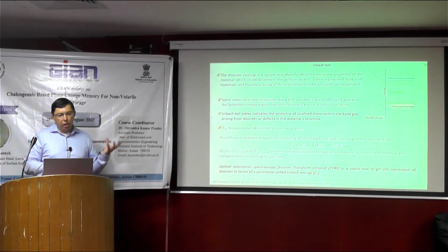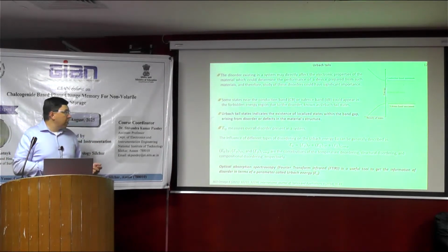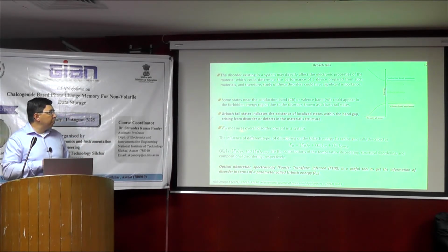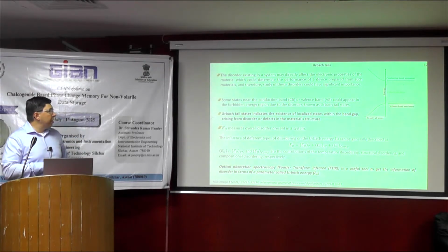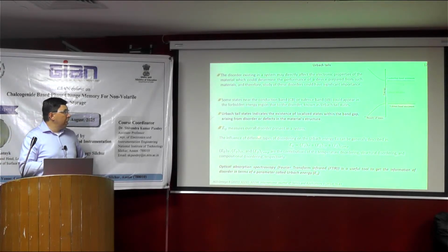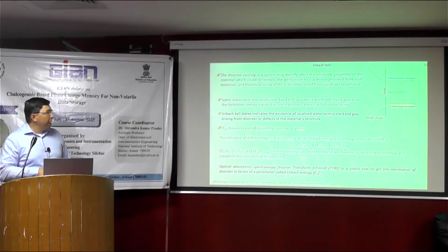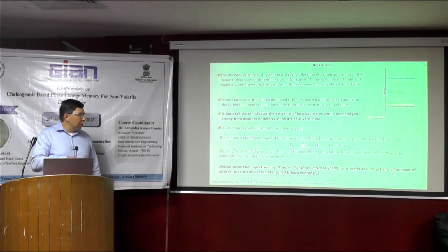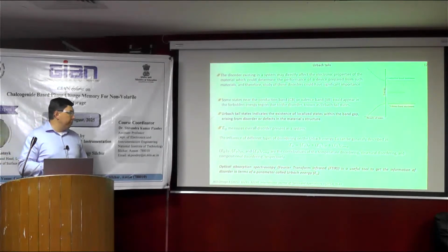Amorphous materials are highly disordered and also have different defects, like maybe voids. And E_U, the Urbach energy, measures the overall disorder present in a system. There are different types of disorder which influence the Urbach energy. It can be temperature disordering, structural disordering, and compositional disordering. So the Urbach energy is a function of temperature, structural disordering, and compositional disordering.